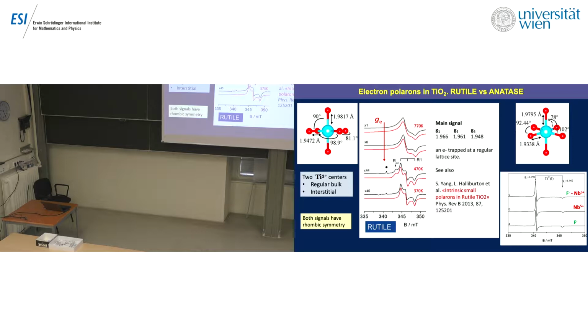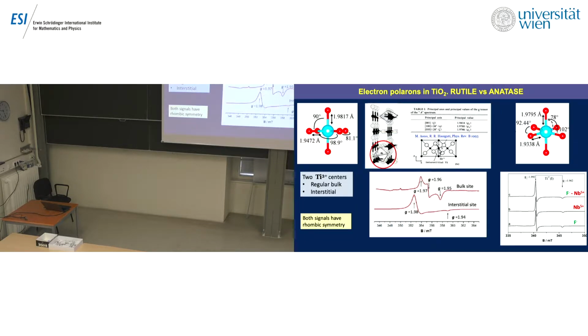There is a series of works on single crystal rutile performed by the group of Larry Halliburton in the United States, and this is one of them. There are some small differences in the g values that you record on powders, but I must not discuss it now, otherwise it's too long. In any case, we are in the area of polarons in rutile. You see that in spite of this small difference, the two spectra are really different from one another. In rutile, there are 2 important sites.